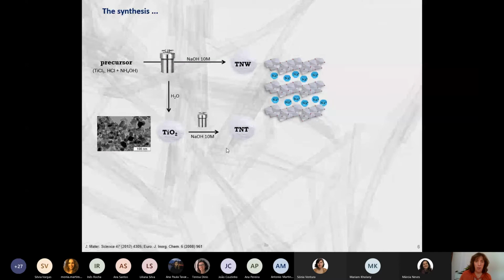But before we think about modifying these materials, we need to prepare them. How? Well, we have a methodology developed by us. We use titanium trichloride, that is a non-toxic material. We prepare a precursor, which is then submitted to hydrothermal conditions. And if we use sodium hydroxide, we will be able to prepare titanate nanowires.